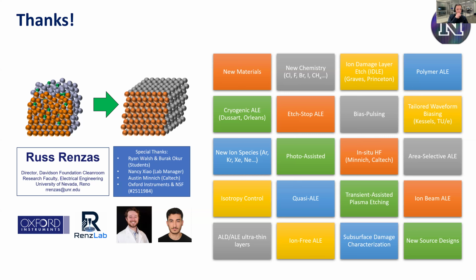Yeah. So first off, all of our experiments are done over many cycles. So we don't run one cycle and then measure thickness. And realistically, if the thickness change is less than about 10 nanometers or so, the students will just rerun it with more cycles. You can actually get into certain things with cycle dependencies, but I'm going to hold off on that for now. So we'll generally run 80 cycles as our standard in our lab. If you're getting a quarter nanometer or so etch per cycle, that's going to give you about 20 nanometers, and we'll measure that in a profilometer.